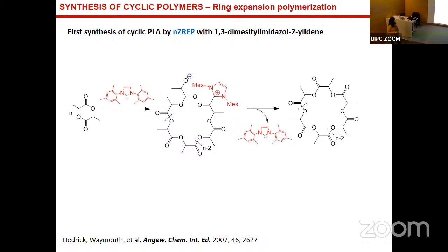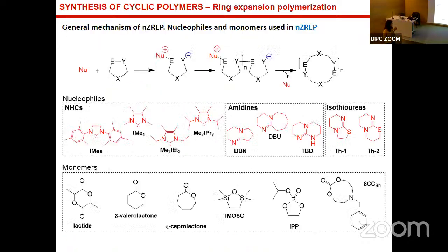He demonstrated in further experiments that this is probably a zwitterionic mechanism, in which the nucleophilic attack of this catalyst on the monomer creates this growing chain with the two ions here, the zwitterion, negative and positive. They travel together, and then more monomer is incorporated into this cyclic structure, and the ring expands upon certain conditions. The catalyst is released and the cyclic polymer is formed with no linker, only the same monomer. This has been very important in the literature because of the importance of these polyesters in industry, and there is a lot of research on this topic.